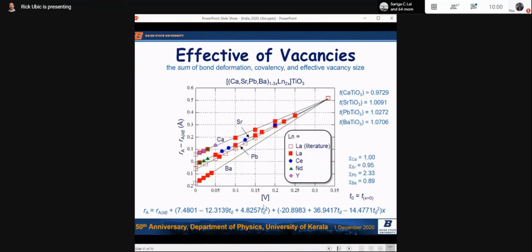Okay, so what we've done here is we've got several families of rare earth doped divalent titanates. So calcium, strontium, lead, or barium, lanthanide doped titanate. So the lanthanide series were lanthanum, cerium, neodymium, and yttrium. And it almost doesn't matter because all of these, which I was astounded when I saw this, they all form on the same lines for a given divalent species. You get just 4 lines here, not a bunch, right? So this is a very key figure because it shows us, number one, that they are all on lines. So it doesn't even really matter which rare earth you use.